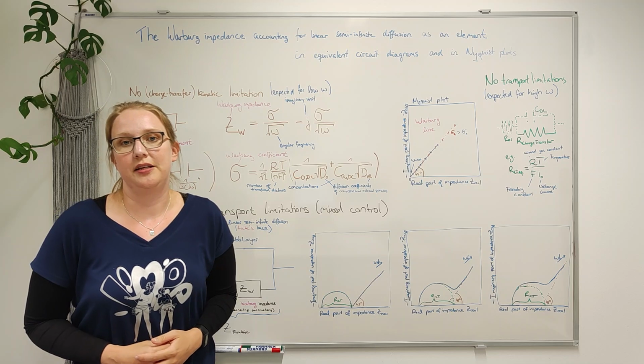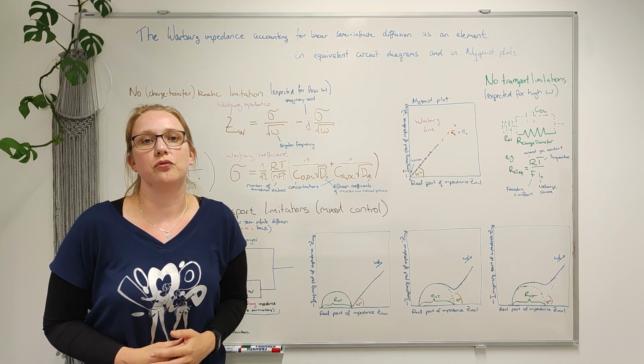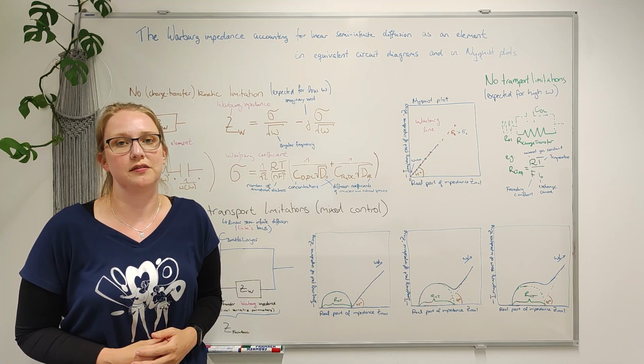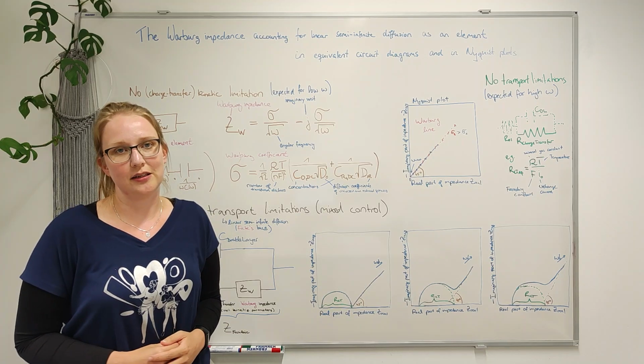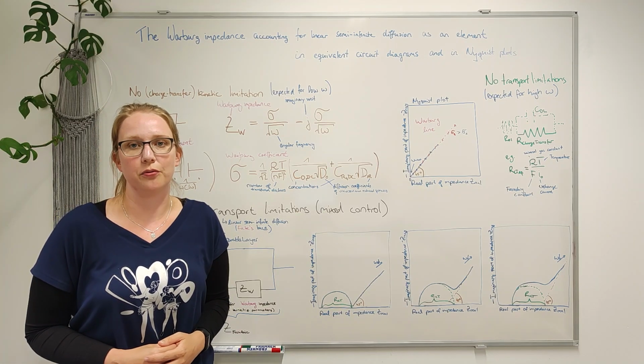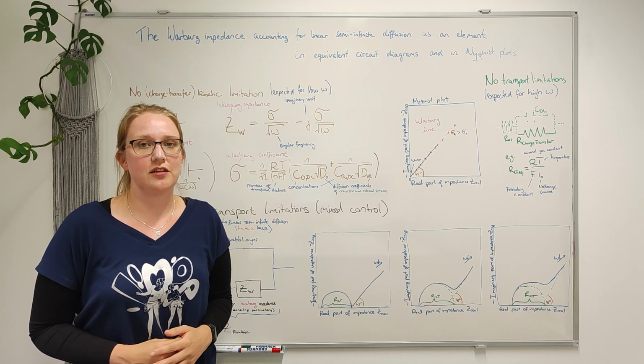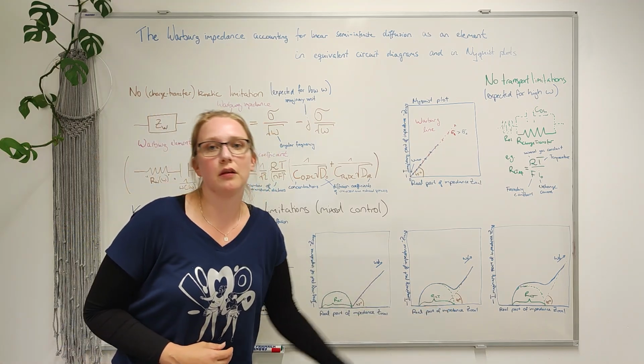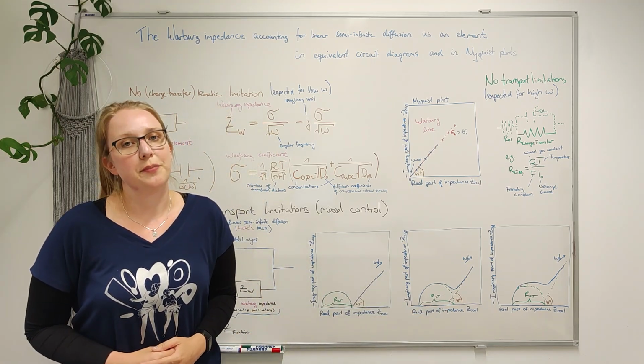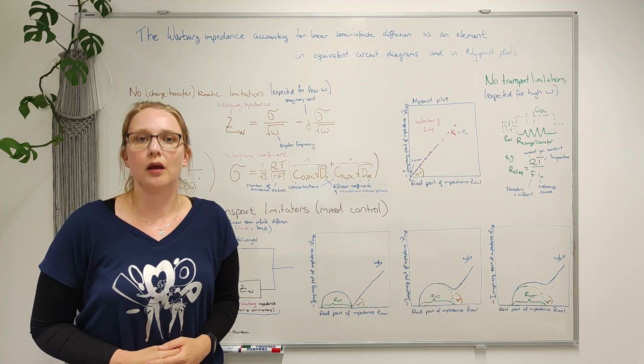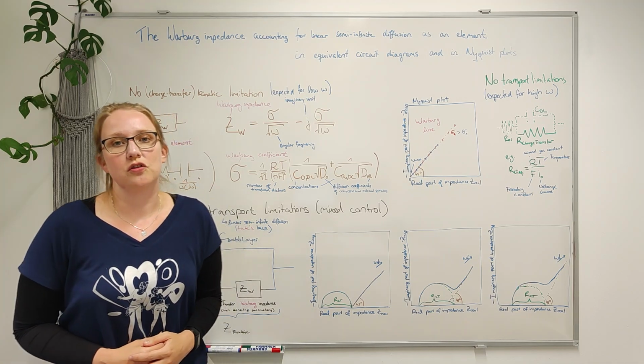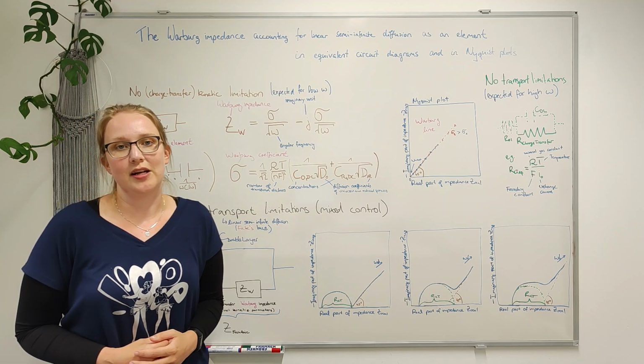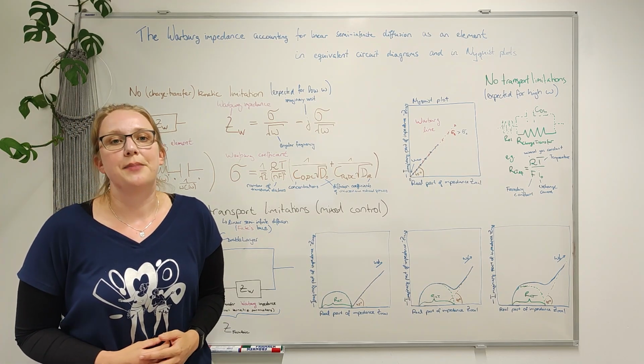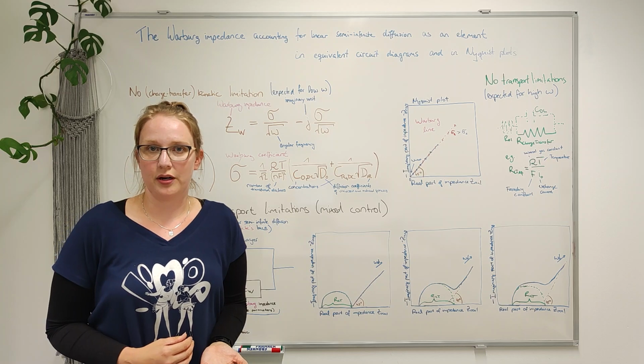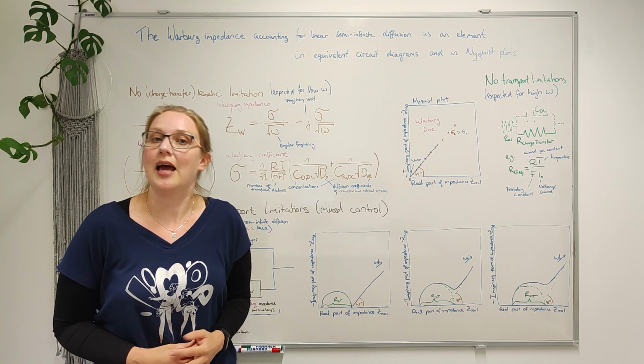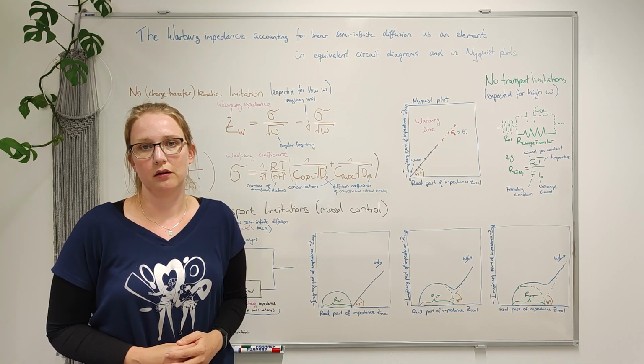Under certain circumstances, it is possible to extrapolate to the real axis intersection of the initial semicircle and thus estimate the exchange current densities of the underlying process. Note that the base point of the straight line on the real axis also depends on the double layer capacitance. The frequency at which the transition between the semicircle and the straight line occurs, or the overlap, depends on the concentration of reactants and products, on the exchange current density and on the overpotential.